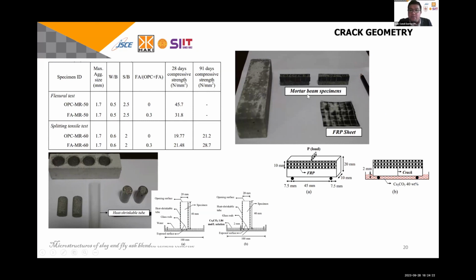And then for the flexural specimen, we apply oven dry treatment, and for the splitting test, we apply saturated condition. I mean the specimen was immersed in water for at least 24 hours before the diffusion test. So in this case, we will have absorptivity, and the last one we will have diffusivity.